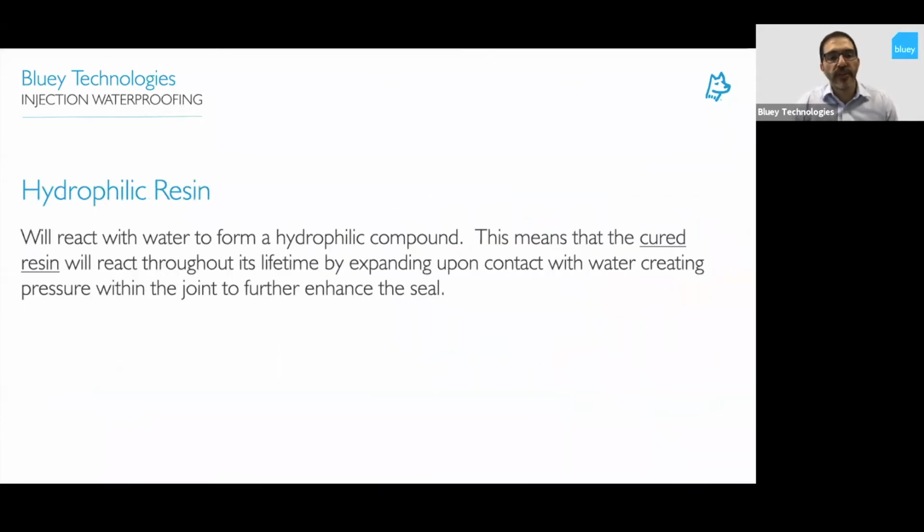So hydrophilic resins, this is a term that you'll hear mentioned quite often. These will react with water to form a hydrophilic compound. And what we mean is that cured compound will then react throughout its lifetime with water to expand and create pressure in the crack. So it relies on sealing the crack by expansion and sealing the water from getting through via compression. So it creates pressure in the joint to further enhance the seal. So hydrophilic resins are alive and active, and they'll pressurize that seal.